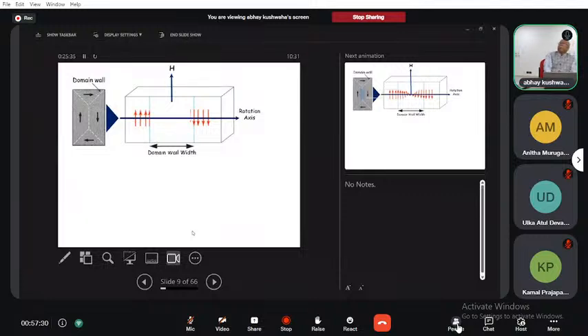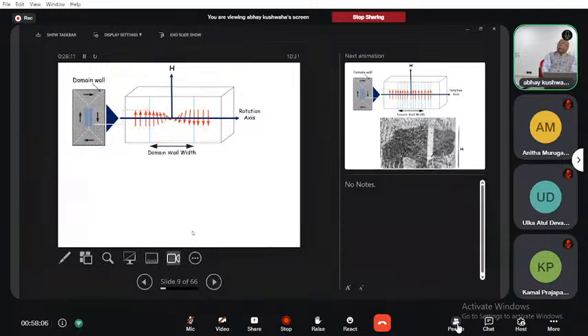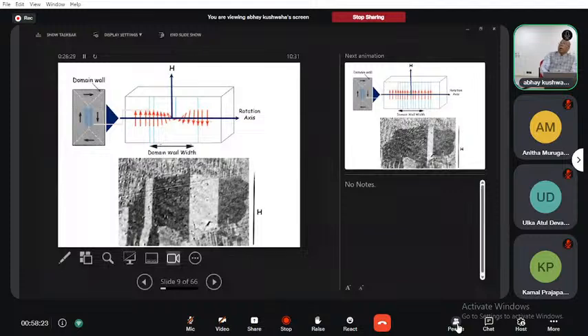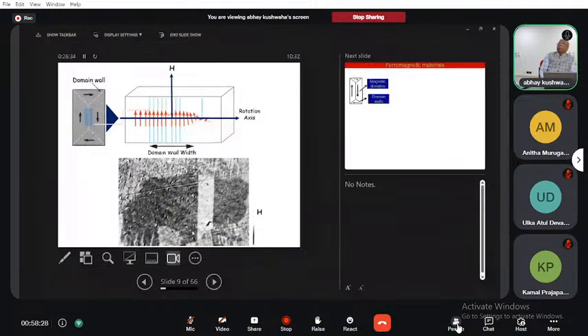But if we exaggerate this domain position, it is something like that. It is not a very sharp line. It has some width, which is called the domain wall width. And this domain wall width is also taking a major role for a material which has to be a soft magnet or a permanent magnet. So if we now apply a magnetic field in this one, you see there are regions in between the two domains, where the magnetic moments are oriented and going from one position to the other position, and it is inverting at the other end. And when we apply a magnetic field, the domain wall movement is taking place, and you can understand how this movement is taking place. So now it is moving towards the right hand side, and it becomes a one domain structure.